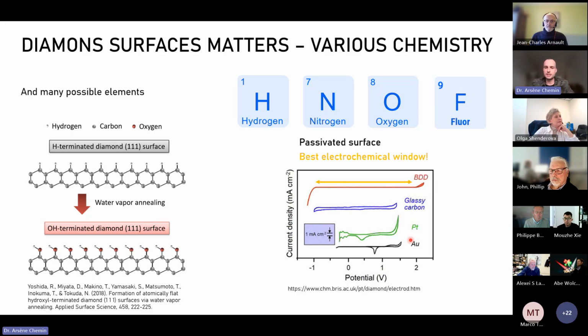And all this is very interesting because by using this kind of termination of diamond, you can actually have a very nicely passivated surface. One good example of that is the use of boron-doped diamond for electrocatalysis. If you look at this diagram showing the current density of various electrodes depending on the potential that you apply, you can see that the boron-doped diamond in red here is flat on a very large potential window. It's actually one of the largest potential windows you can achieve. So between -1 and +2 volt versus, I think it's a hydrogen reference here, you don't have any reaction. Because if you look at platinum or gold, you can see those features and those peaks that actually correspond to redox reactions. But the diamond surface, because it reacts so little with the environment, remains completely flat.